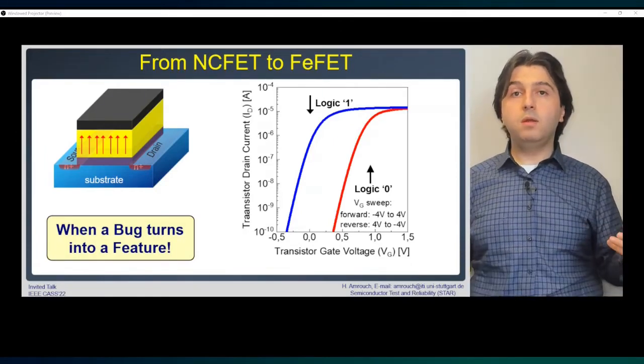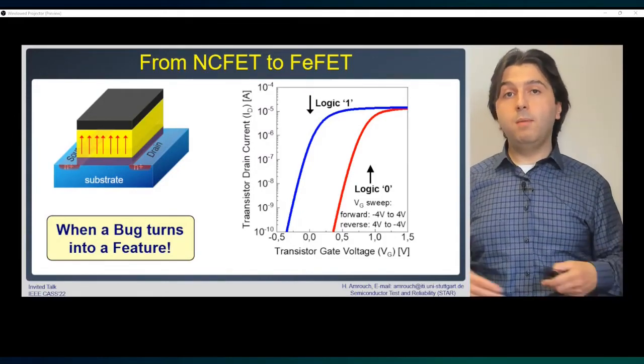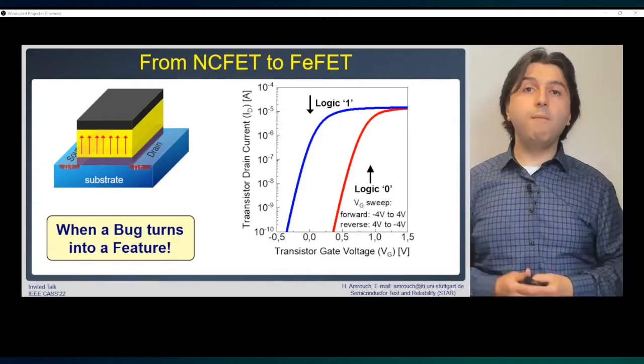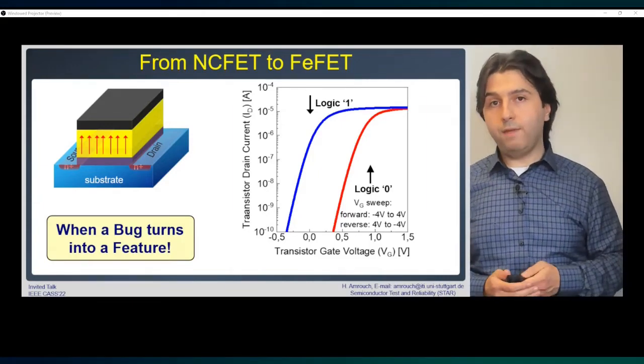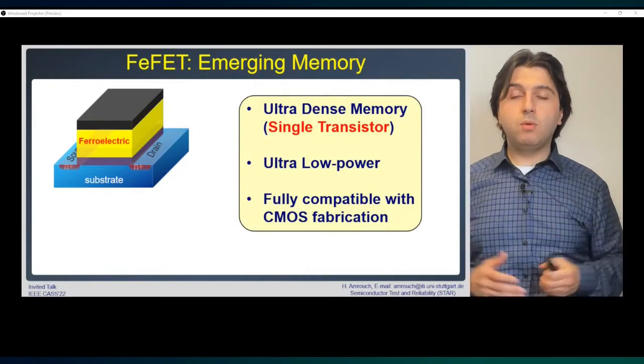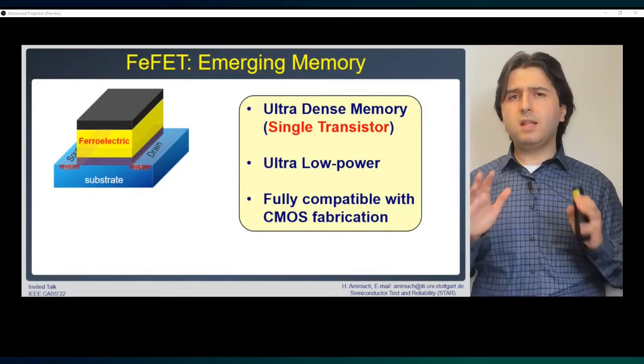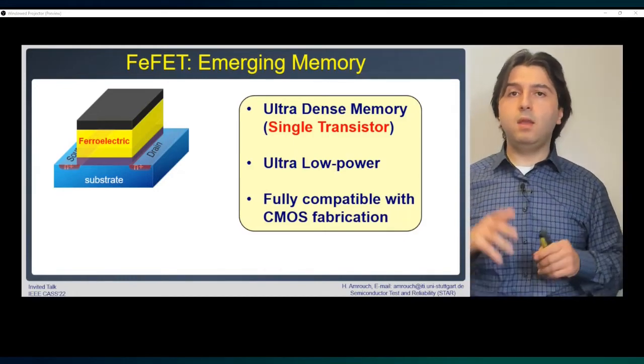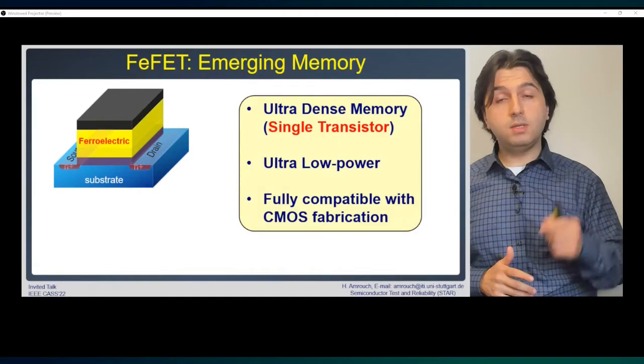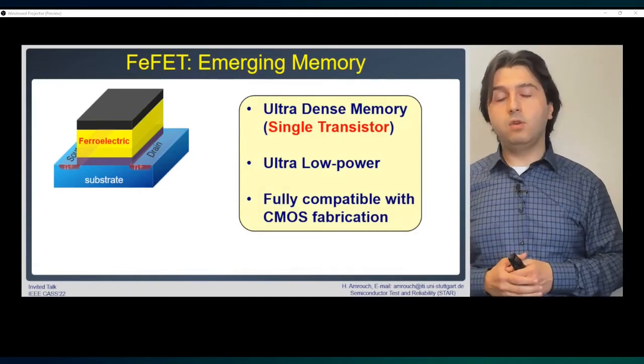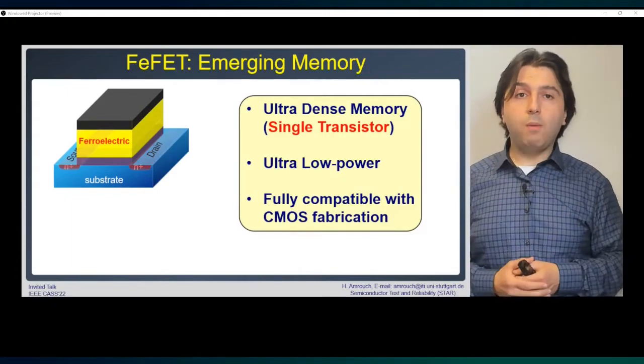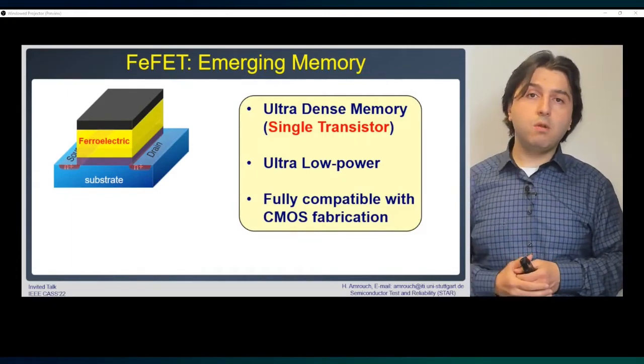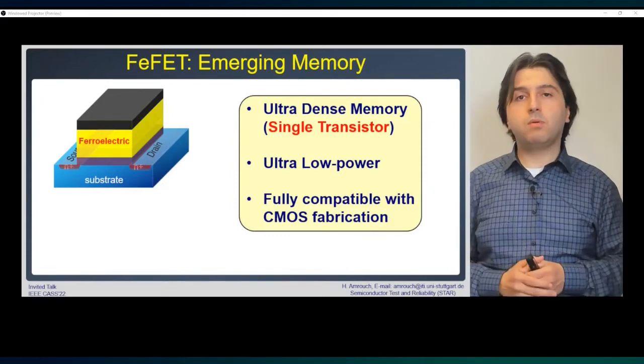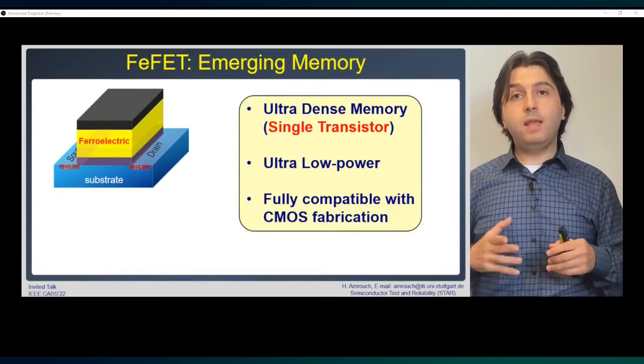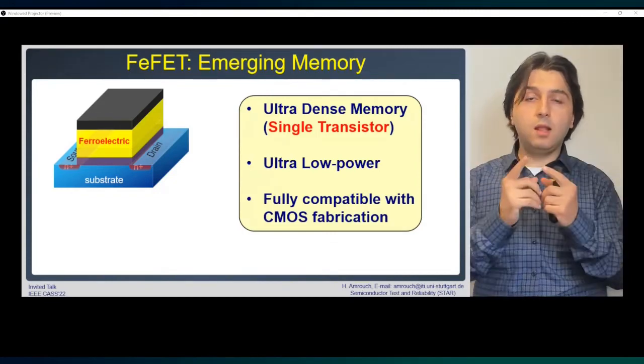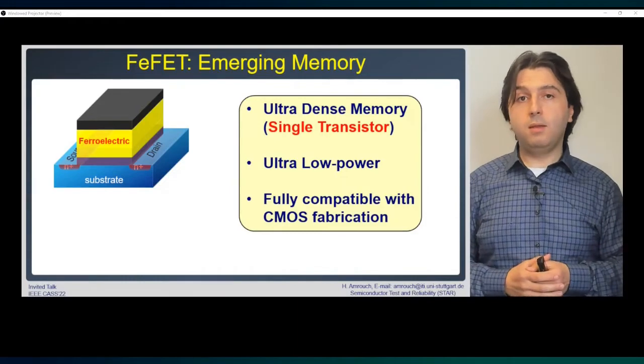And more interestingly, this memory is a non-volatile memory because it is a remnant polarization. The polarization will remain after removing the electric field. Let's imagine together if this technology becomes reality, and there are lots of demonstrations from GlobalFoundries here in Germany, also from Intel recently, and many companies, also TSMC, are investing a lot in this technology. The promise is clear. Again, it's compatible with CMOS because the realization of ferroelectricity in hafnium is possible through zirconium doping. On top of that, replacing our 6-transistor SRAM with a single transistor to create a memory is indeed extremely attractive and amazing.